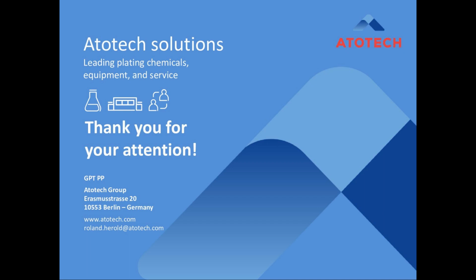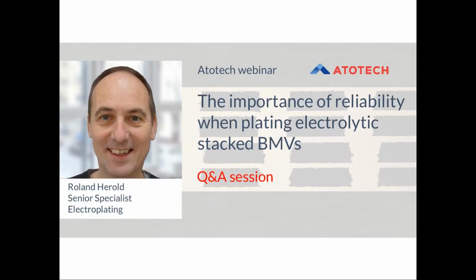That the target pad has to be clean is logical, I think, to get best adhesion and a very good reliability of the interface integrity. But here we also need to avoid a very strong roughness. So when you have to clean target pads from any kind of residues from direct plating processes like carbon or graphite, then in this case, maybe you need to consider to keep the roughening effect of the cleaning very low.